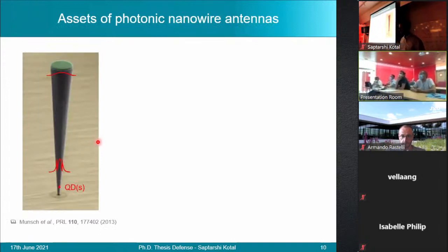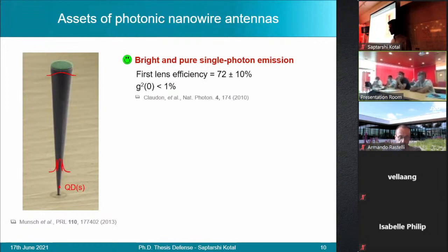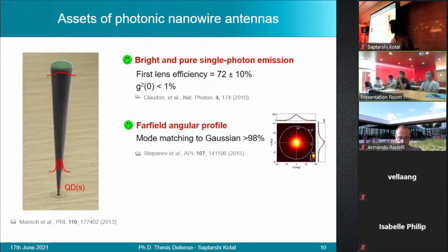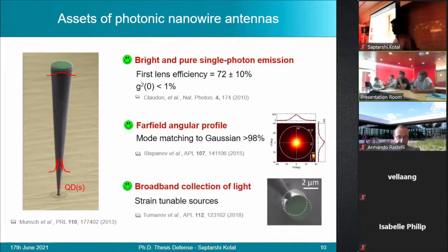Now, another interesting geometry that we use is what we call the photonic trumpet. It functions identically to a photonic needle as seen earlier, except in this case, the guided mode is expanded within the material rather than outside it. Now, such nanowire devices have enabled the fabrication of bright and pure single photon sources. They help to funnel the spontaneous emission into a very directional beam, having a Gaussian profile. Finally, they offer a very broadband operation, which helps to simultaneously collect the emission from various detuned quantum dot transitions. Finally, this broadband nature of these nanowires has also enabled to develop a wavelength tunable single photon source recently.